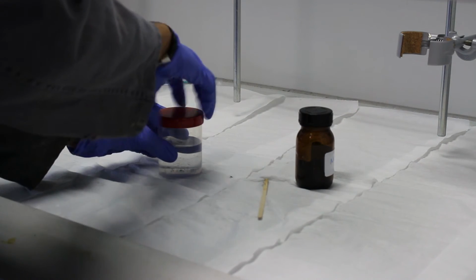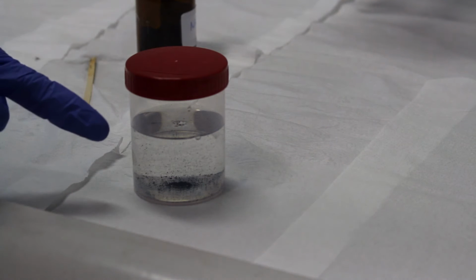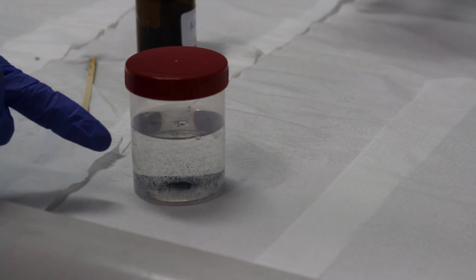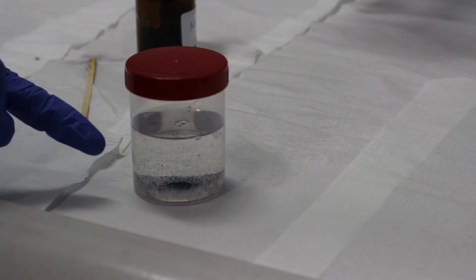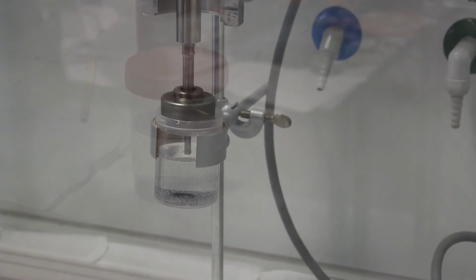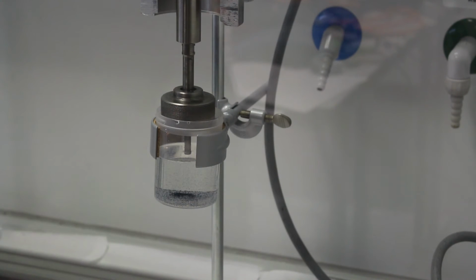And as you can see, there are still huge agglomerates of nanotubes lying in the water. So the dispersion is not good at all. And what I'm doing here now is ultrasonication. Basically, the tip of this device emits ultrasonic waves, which leads to this cavitation process. So it's like you are inputting energy into the water, and due to the cavitation, there are shear forces, and you will see what this means in practice.